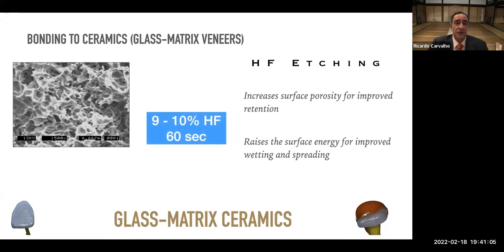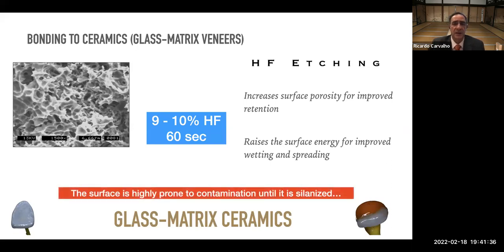And the recommendation, as we know, we have different types of ceramics. So feldspathic or glass ceramics, even though they are based on feldspathic composition, but of course, from manufacturer to manufacturer, they vary. And the recommendation that is apparently good for all of these in terms of increasing porosity and increasing surface energy is to utilize a 9 to 10% hydrofluoric acid etch concentration, and the application time is 60 seconds.